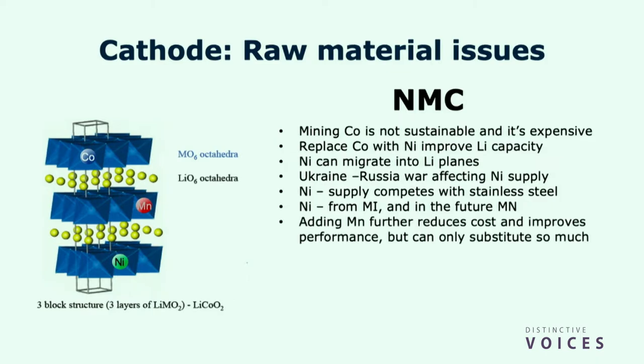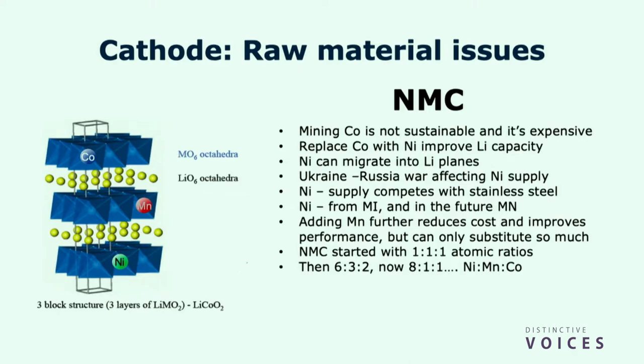Again, we can add manganese. That's cheap and non-toxic. That helps. But you can only substitute so much manganese to get the desired performance. So basically, NMC started with atomic ratios of 1 nickel, 1 manganese, 1 cobalt, trying to get rid of cobalt. So they went to 6 nickel, 3 manganese, 2 cobalt. Now they're currently working on 8 nickel, 1 manganese, 1 cobalt. But the problem is, sure, that's great, you're reducing the cobalt, but you're not getting rid of the cobalt, right?